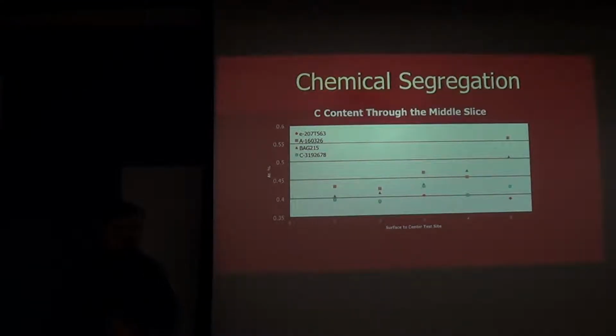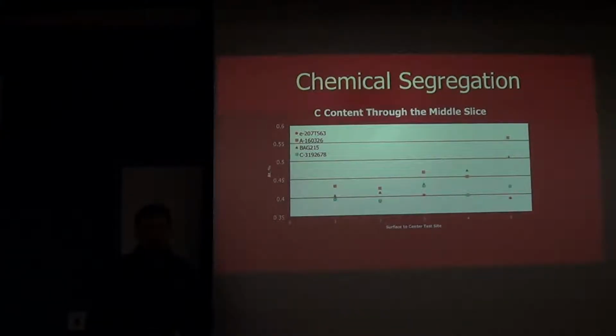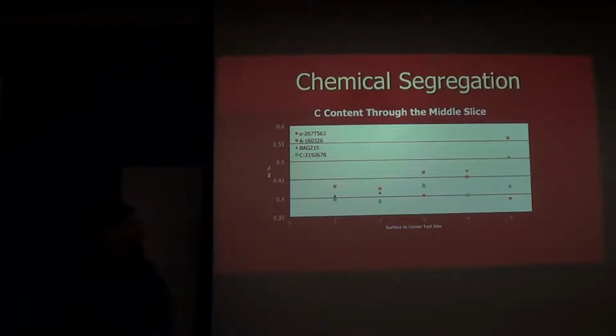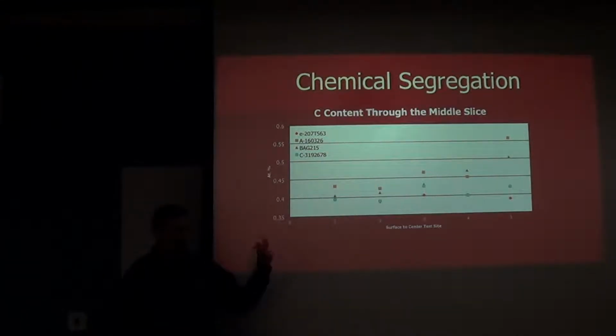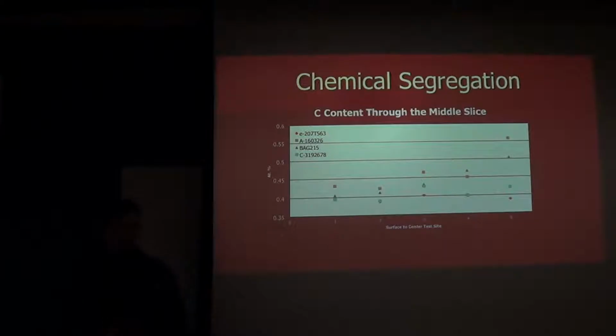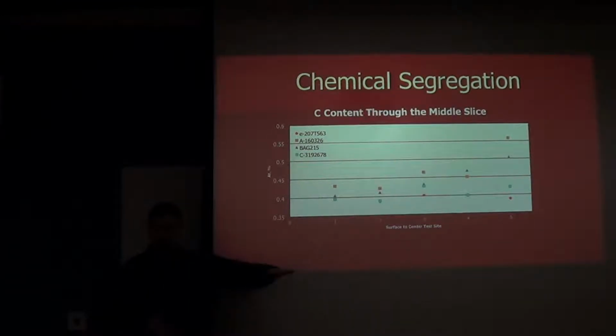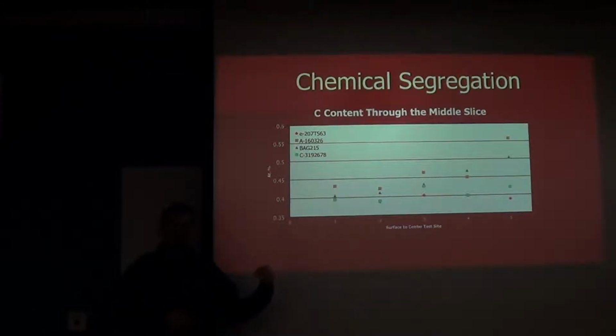To increase your carbon by 0.15%, that's a lot. That's a big difference. And that's not because the mill made any changes in additives, just because the carbon was mobile and could move throughout the cross-section during solidification. So I don't have any real control over this as a forging guy, and I can't really change it. Once the ingot is solid, it's solid, and I can't really redistribute those elements.